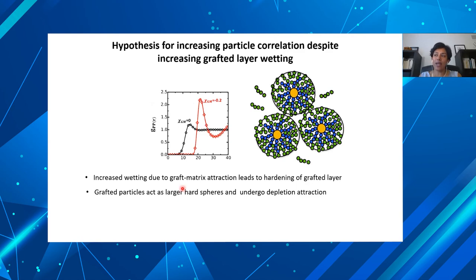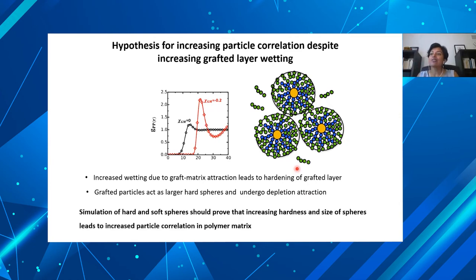So why is that? Here was our hypothesis, and I'll show you how we proved it. Essentially, what we found is that the grafted particles, when the matrix is wetting them, so you see the matrix chains are inside, you remember that the concentration profile expanded. So the grafted layer that is like this, when the matrix is penetrating it, expands to fill in a lot of matrix. So it becomes larger and harder. So we think that the increased wetting leads to that increase in size and hardening. And then they end up acting effectively like hard spheres instead of the soft, hairy particles. And then those hard spheres and these tiny polymer chains around them essentially act like a system of colloids and tiny polymers, and we expect to see depletion attraction and higher particle correlation at higher distances. So that's what we wanted to prove.